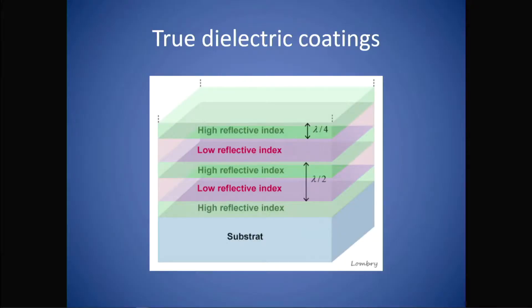The dielectrics are a different matter. Most modern dielectrics are not made with that aluminum reflective layer. They're made with dielectric coatings — alternating metal oxide layers of different refractive indices — and there's literally hundreds of these layers, and they combine to give you almost 100% reflectivity and a very, very hard surface, so you can clean this every single day and it's not going to damage it.